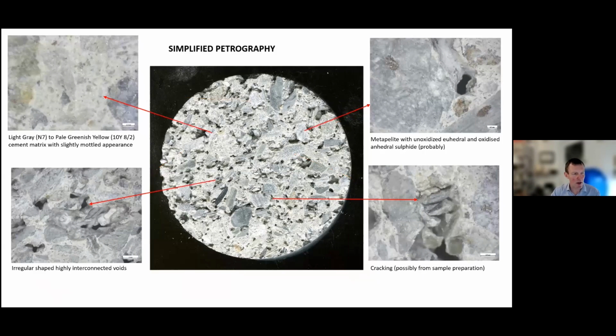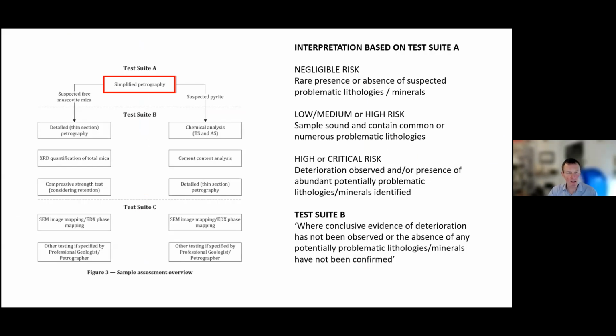We can also look at the cement matrix. The top left-hand panel shows that, and you can see there's a scale bar that's 0.2 millimeters in that panel. It quickly reaches the limit of what we can see with basic optical microscopes. We look at the void contents, any cracks, and anything that might be there that could be considered deleterious. And at the end of that, the idea is that the professional geologist should be able to assign, hopefully, the risk assessment in terms of it being negligible, low, medium, high, or critical, based on what they can determine.